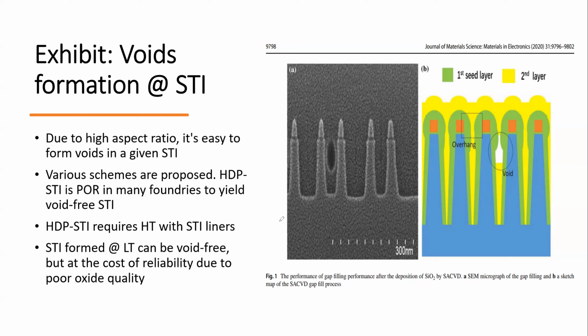To solve this problem, if you do a low temperature process, say even an ALD process, you can fill it up. But what's wrong with the low temperature process? It can be void-free, but the oxide quality is not good. Because when you form an STI, which is SiO2, the SiO2 needs to be very high quality. How do you make it high quality? You need to anneal at a very high temperature. If you don't do it, it looks good right now. I say, okay, this is good. But later on, in a later process, this becomes weak.